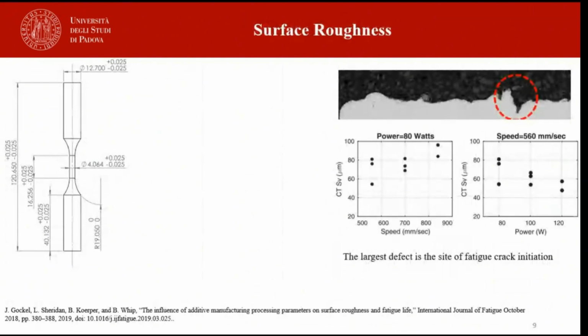Surface roughness is one of the detrimental factors that impact fatigue life. In this paper, they investigate the effect of maximum depth of surface roughness on fatigue behavior of materials in as-built condition. For this purpose, samples were fabricated using different laser power and laser speed to achieve various surface roughness. After printing, samples underwent stress relief heat treatment to remove residual stress, ensuring that only the effect of surface roughness would be assessed.